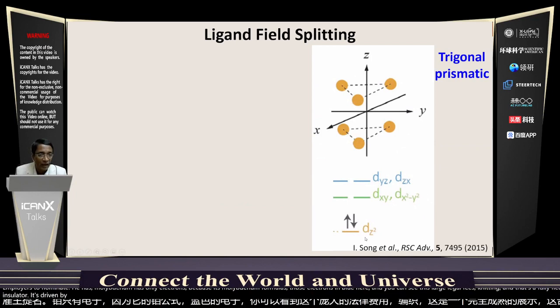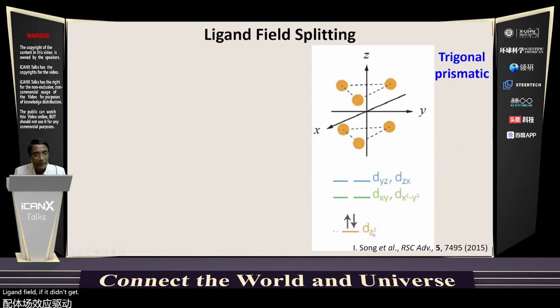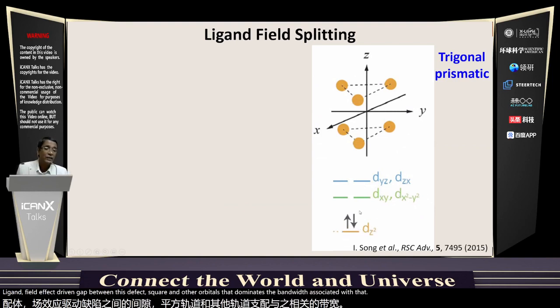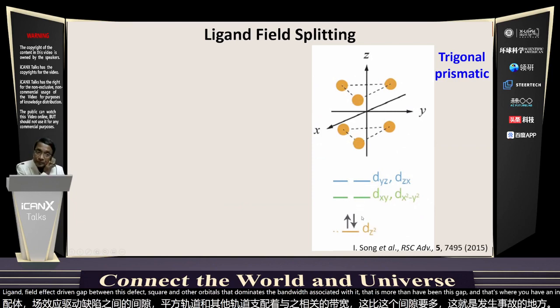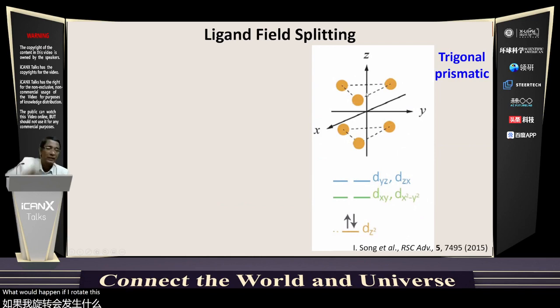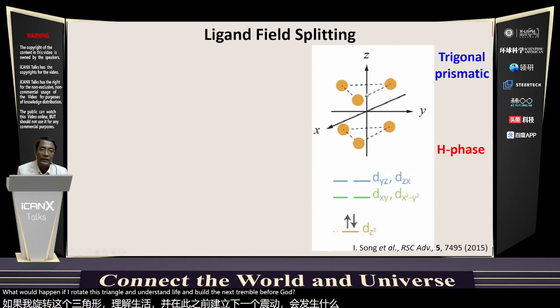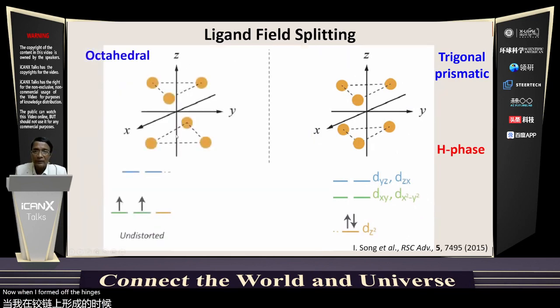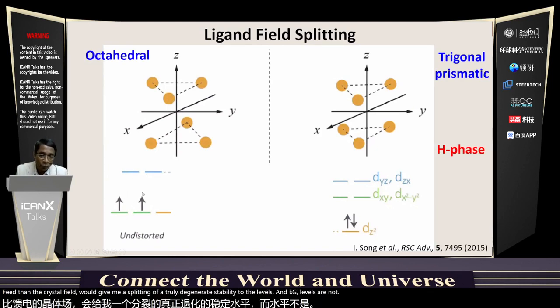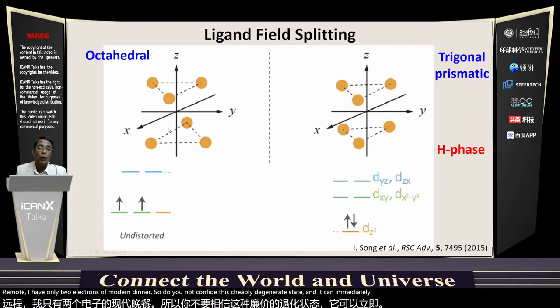It's driven by this large ligand field effect driven gap between this dz square and the other orbitals that come next. The bandwidth associated with that is smaller than this gap, and that's why you have an insulator. What would happen if I rotate this triangle around or slide and bring the next triangle to form the octahedron? Now, when I form the octahedron here, we know that if it is a perfect octahedral field, then the crystal field would give me a splitting of a triply degenerate state below, T2g levels, and eg levels above. Remember, I have only 2 electrons of molybdenum, so they will occupy this triply degenerate state, and you can immediately see why this particular state will be metallic, because it's a partially occupied state.